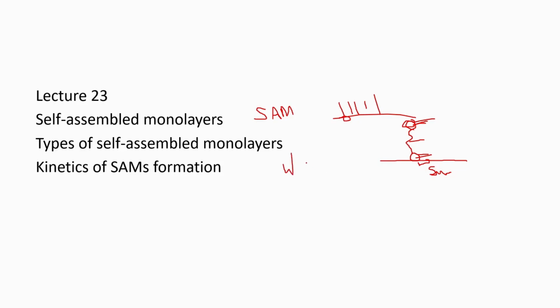In the absence of water, there will be incomplete attachment, but in the presence of excess water, there will be siloxane bond formation in the solution. So we need an appropriate amount of water. This is basically a chemical reaction wherein the ligand is interacting with the surface to form a covalent bond.